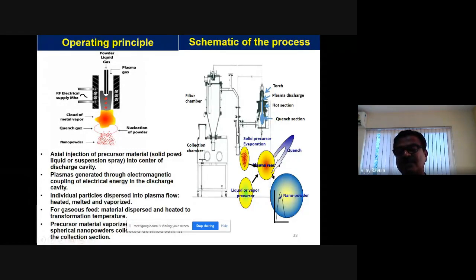and then it comes to this. When you are passing the gas, the bigger particles settle down over here, and then the finer particles go into the hopper and get collected. So for anything, the critical thing is you need to play with the metal flow, gas flow, and the power of the plasma, because the residence time is very, very small. So you have to play with these things to get a desired size and a desired size distribution.